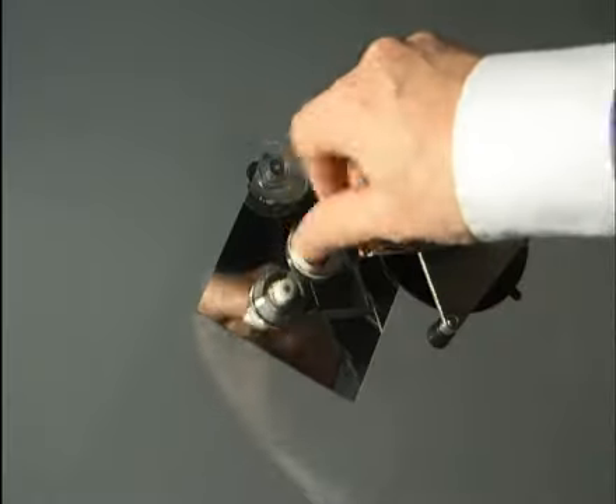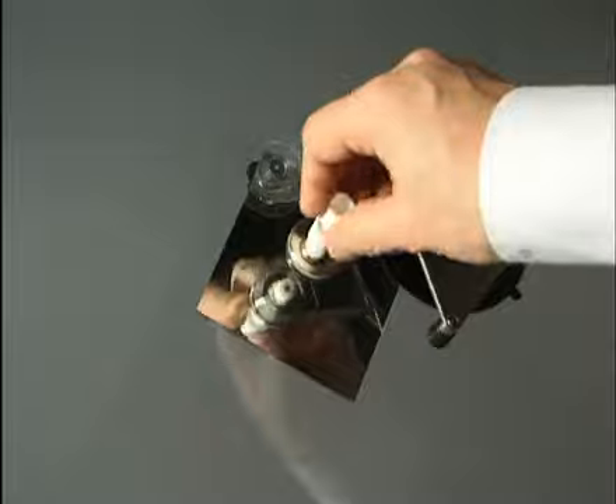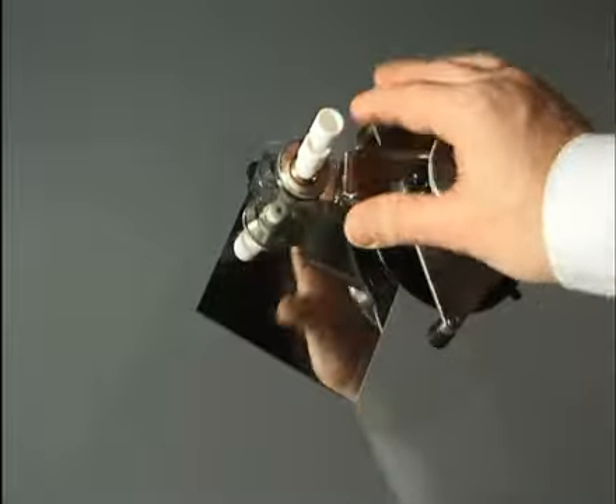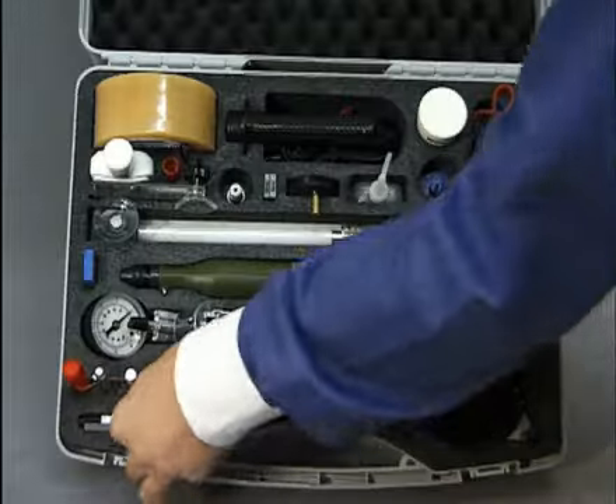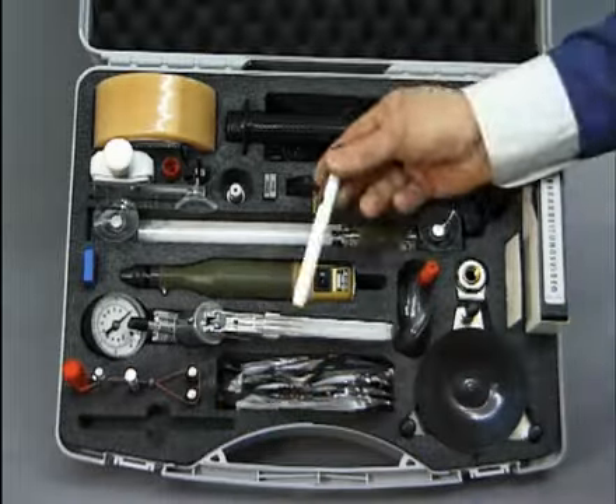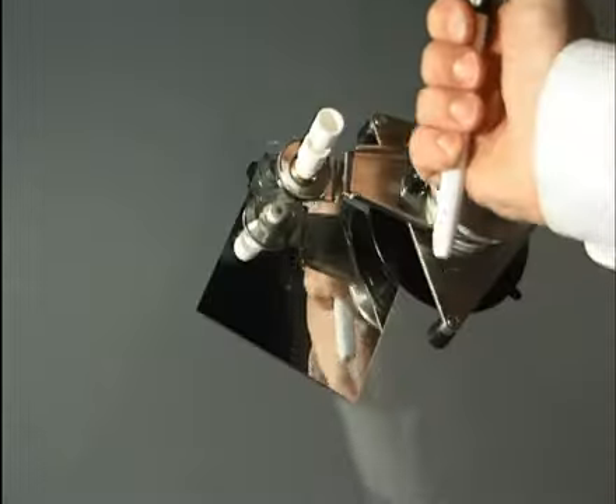If you have the impression that the damage is completely filled, move the filling resin cylinder from the damage and check with the torch from all sides to be sure that there is really no air left in the damaged area and that it is completely filled with resin. Damage should be filled with a substantial body of fill resin to prevent spreading during curing due to polymerization shrinkage. But in any case, do not fill the damage excessively.